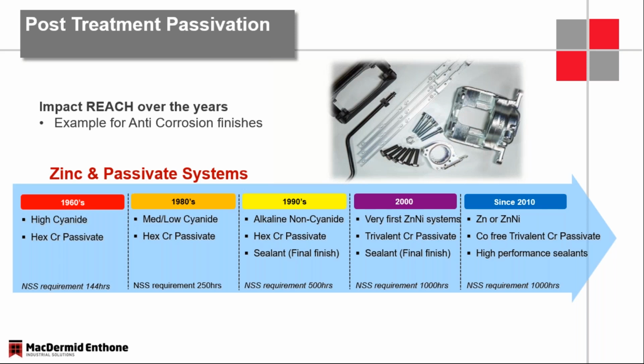In the 1990s, we started coming up with cyanide-free zinc plating solutions, and they had some of their own hiccups in the beginning, such as delayed blistering. But we also started to put on final finishes like silicated sealants for extra corrosion resistance. You get to about 500 hours or so. In the later 1990s and 2000s, zinc alloys became popular. Extra corrosion resistance. We started to use trivalent clear passivate solutions. So we were starting to move out of the hexavalent area. And we still were using sealants, but the requirement was about 1,000 hours.